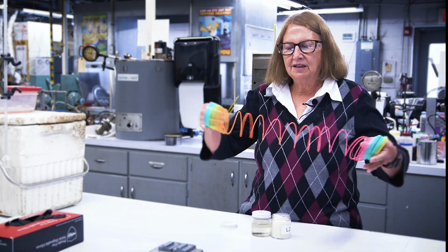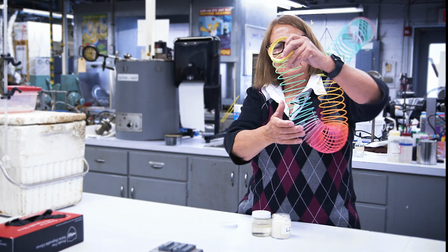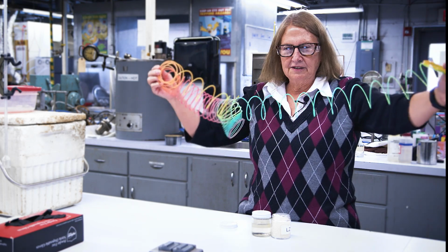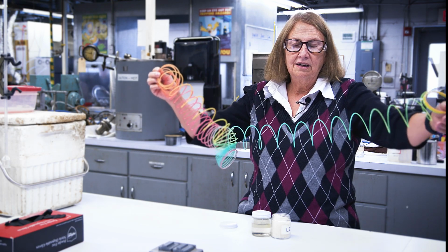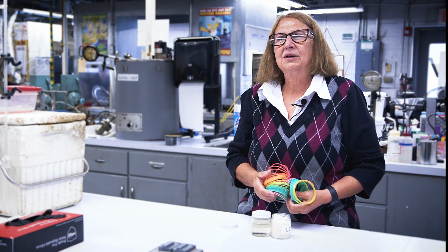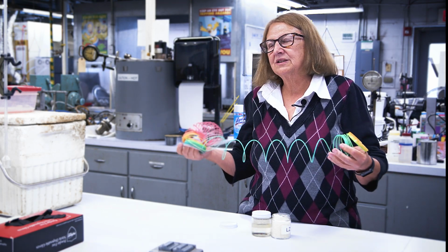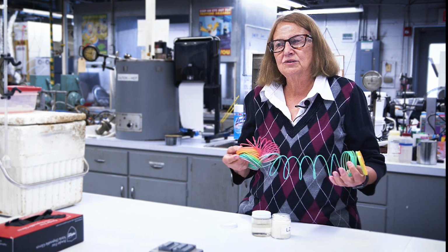What happens to a polymer when it gets hot? Well, the answer is they expand. They get extremely large and they may be very coiled. So they're taking up not a small space now in the oil, they can take up a very large space. And as they expand, and thousands of these are expanding, the impact on the viscosity as it gets hot is they thicken the oil. So as the oil would naturally become less viscous as it heats up, the polymers then expand, and in expanding, they increase the viscosity, thus countering the reduction in viscosity that you see in the oil itself.